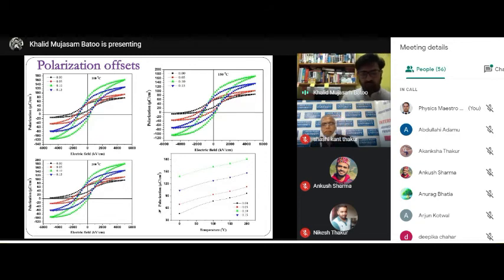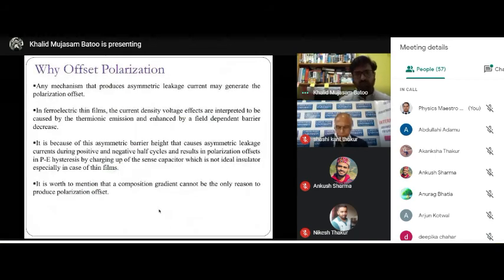That means it was shifting from minus y towards positive y, and that's an offset polarization effect which we observed in this material. The offset was much higher when it was 200 degrees centigrade. Where is it coming from? It's actually coming from asymmetric leakage current which is being generated as we heat the bottom of the substrate.